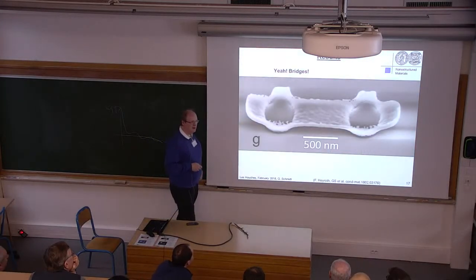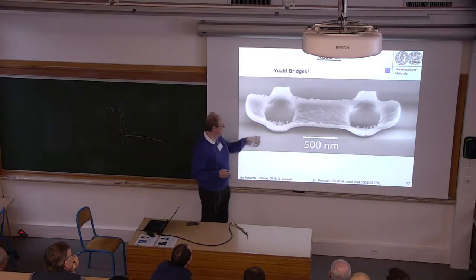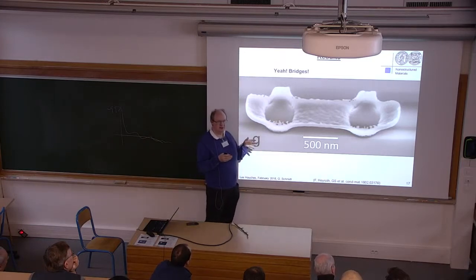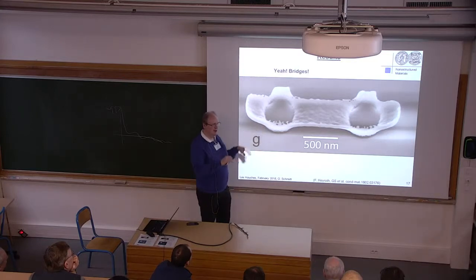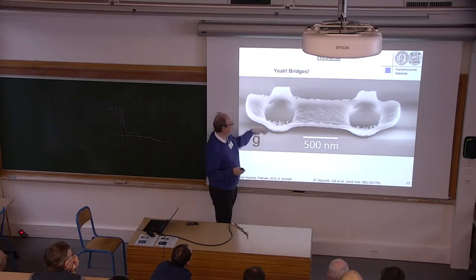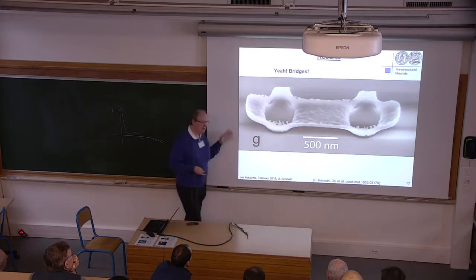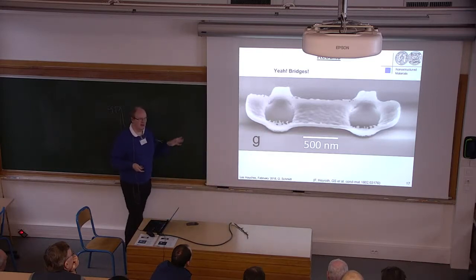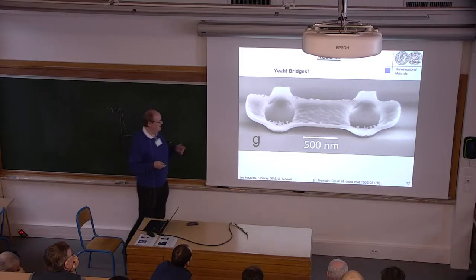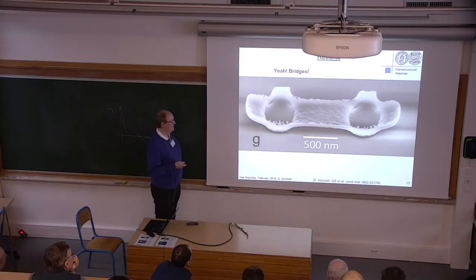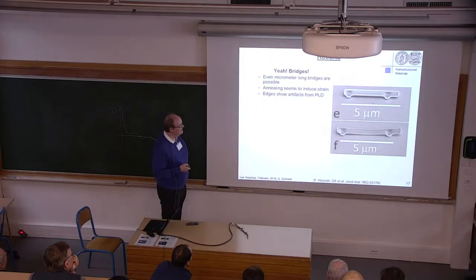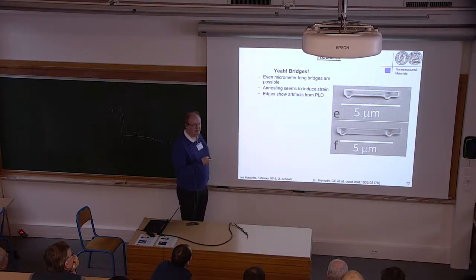Here you can also see that the liftoff is not as nice as it should be. Actually at the edges, the PLD is not a clear evaporation process. You also have some diffusion to the sides, which basically touch the PMMA and it goes upward. But as you will also see, this does not conflict with the magnetic properties of the structures. And you can see, this is a very small resonator, 500 nanometers. The other one is 5 micron.